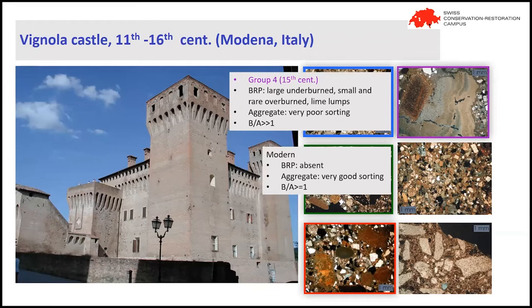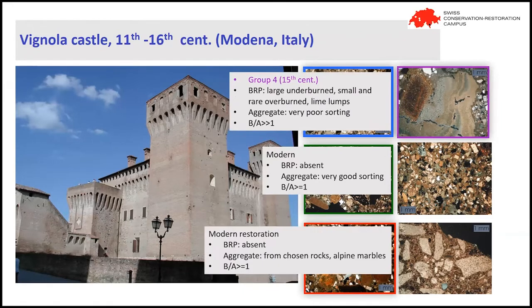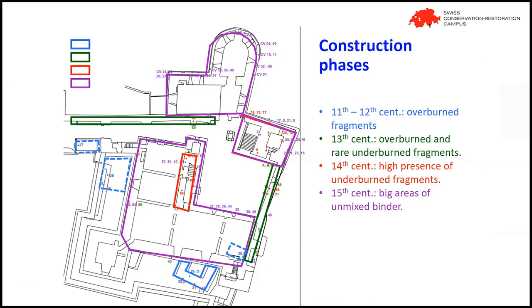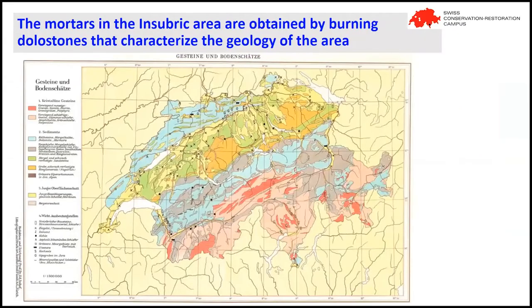We have also characterized two different modern mortars, one that belongs to a modern addition in the 18th to 19th century, and another that was used during previous restoration works. So at the end, we could have different information, and for example, we could identify some structures of unknown age, which have this characteristic of having very many overburned particles, and so these unknown age phases were attributed to the very first phases of the building of the castle.